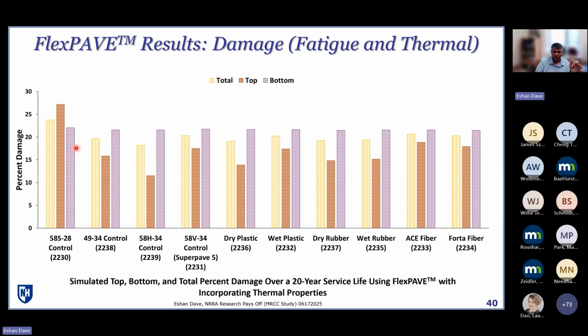If we just focus on near the top, because that's where the uniqueness is in these different mixtures, and that's where you are seeing the most of the thermal action as well. So you can see again a polymer modified mixture doing quite well with substantially lower damage compared to your control, and then a different type of additive showing different responses depending on the type of additive.